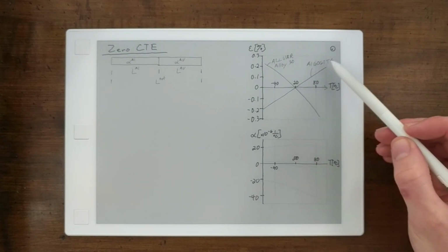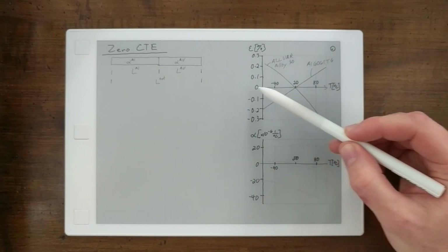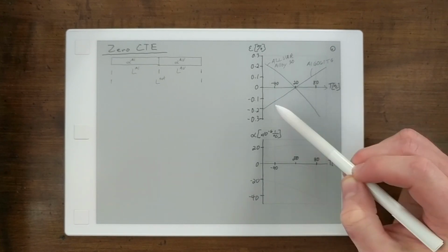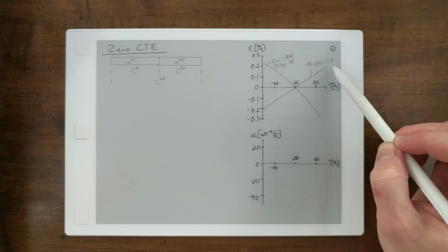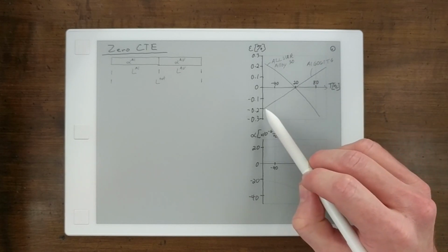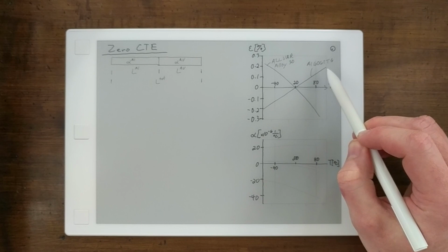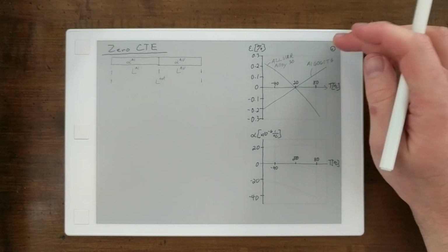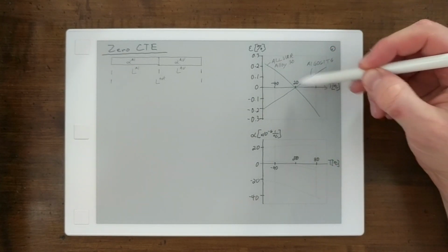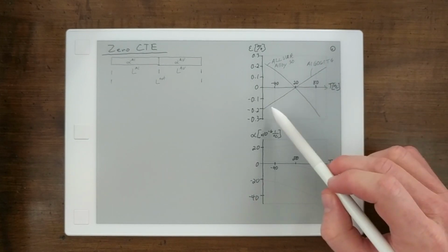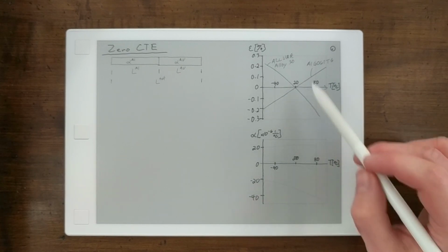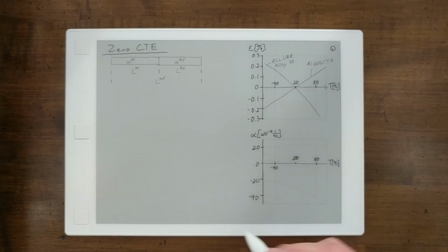And you start to combine aluminum, this is the strain versus temperature, negative 40 degrees C to 80 degrees C. And if you look at aluminum 6061 with a T6 heat treatment, you see that it increases with increasing temperature, and the ALLVAR Alloy 30 does the opposite. You'll also notice that the ALLVAR Alloy 30 has a curvature to it, whereas the aluminum 6061 is very straight, and we'll actually get into the implications of that curvature versus that straight line.